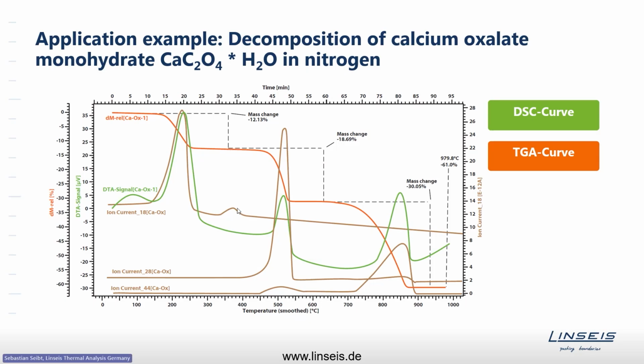There's another little peak on the water line over here, which means there is maybe some water coming out here and going slower to the mass spec. At higher temperature, it goes off. And as said, the first decomposition step is the loss of water. Then you have a second step, which you can see here shows a big effect on the carbon monoxide line, so that you can be sure this is the release of carbon monoxide.